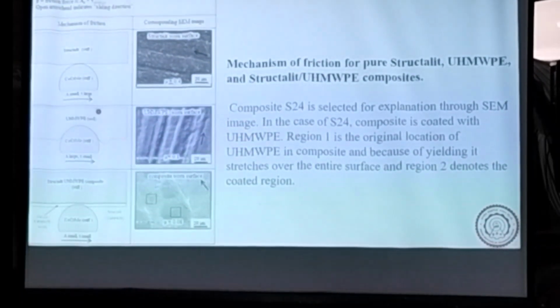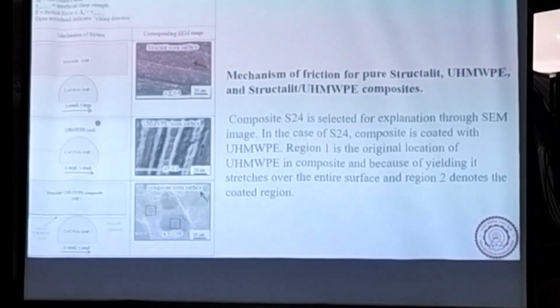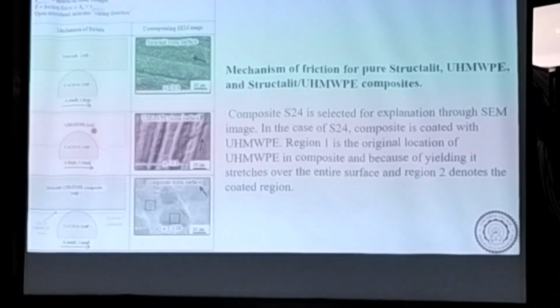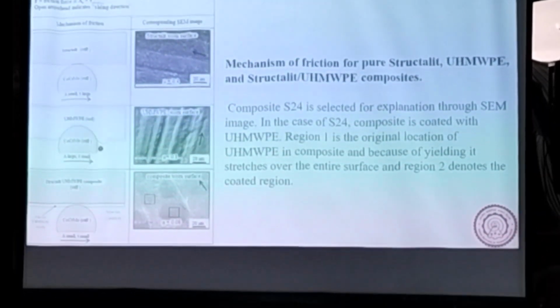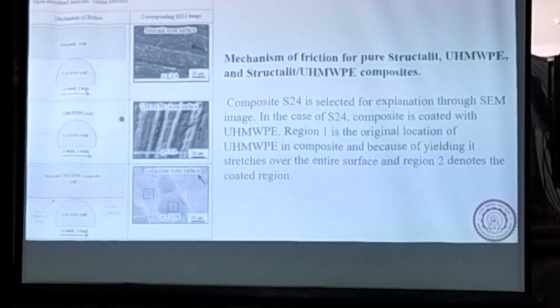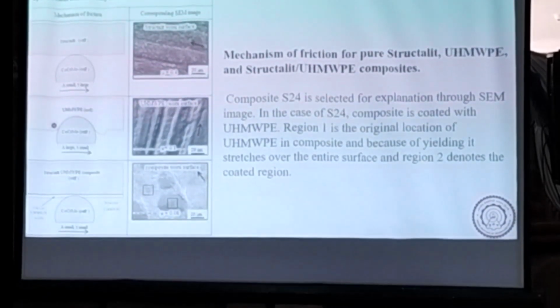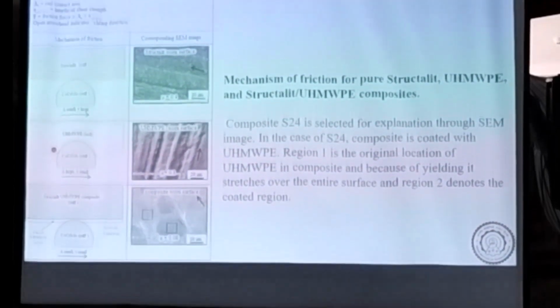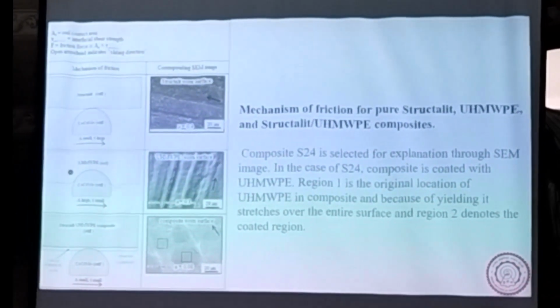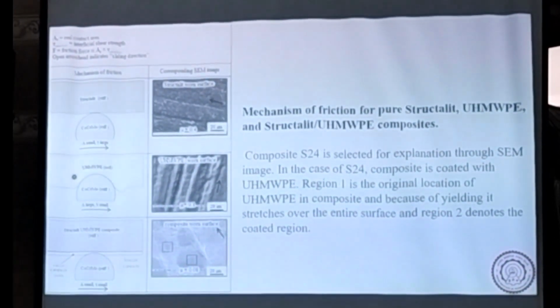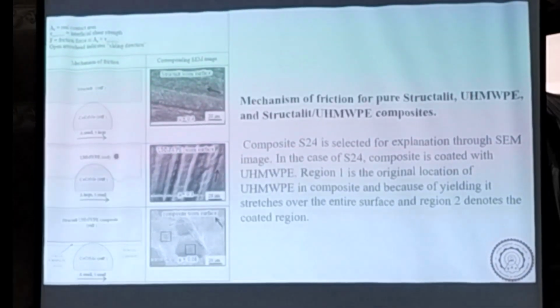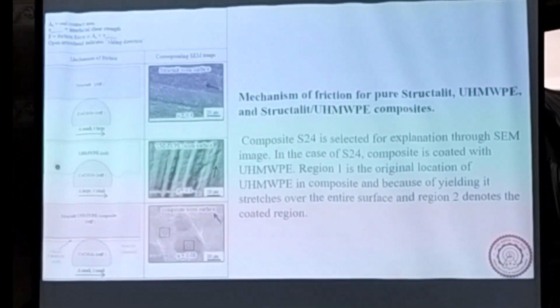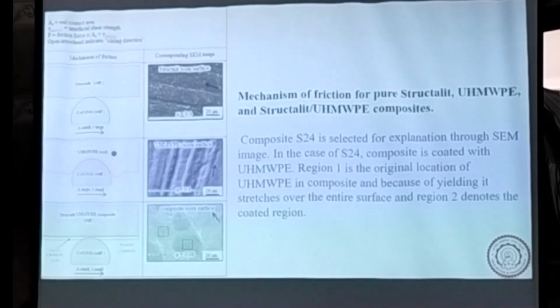Even though the soft material has a low coefficient of friction by nature, in this case the contact area is more, and we also see that the volume of energy dissipation is increased because of its softness. So more material will be deformed, and therefore there will be more energy dissipation here. And that's why the coefficient of friction is large in this case.